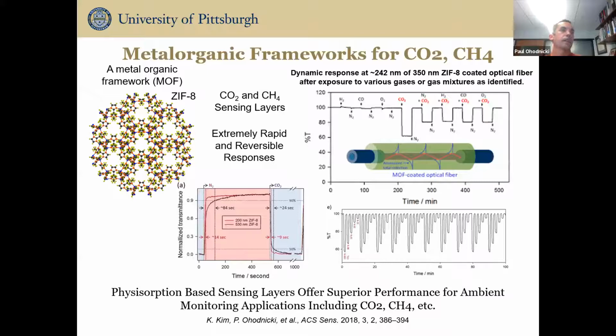So we can also apply sensing layers to fibers, just like we did with the surface acoustic wave, and we can actually apply very similar sensing layers. So this is an example where we're applying a metal organic framework, again for CO2 and methane sensing, but we're applying it as the coating on the core of an optical fiber. We again get to take advantage of the rapid reversible response of the metal organic framework and the selectivity to CO2.